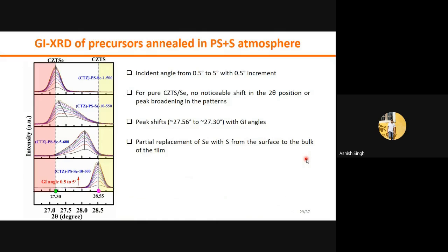Then we moved to make the solid solution of CZTSSe. For that, we used 3 approaches. One, we make the phase pure CZTS and anneal it in a selenium atmosphere. Another approach was to make the phase pure CZTSe and anneal it in a sulfur atmosphere, and the third was to make the metal precursor and anneal it in a sulfur plus selenium atmosphere. From this, we found an asymmetrical peak in XRD. Due to this, we started analyzing the stress of the deposited film.